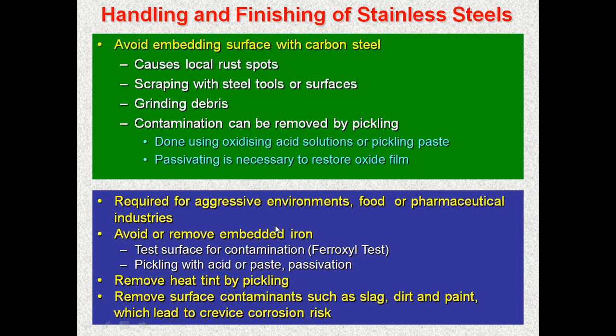And this is very important, and after that you have to also test for the removal of iron by the Ferroxyl test, or you have to ensure that with pickling and passivation such things are removed. And sometimes even the heat tint that is present after welding should also be removed by pickling, and the surface contaminants like slag, dirt and paint, chalk marks, pencil marks, all that should be removed when you are handling a finished stainless steel component for any application.